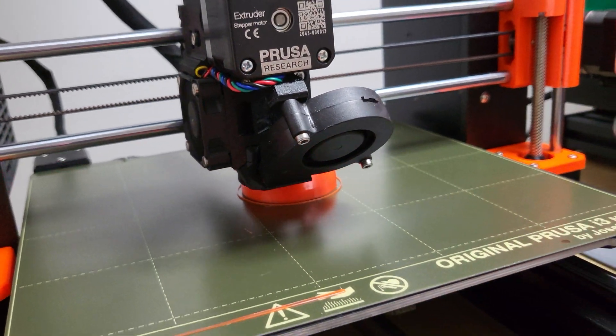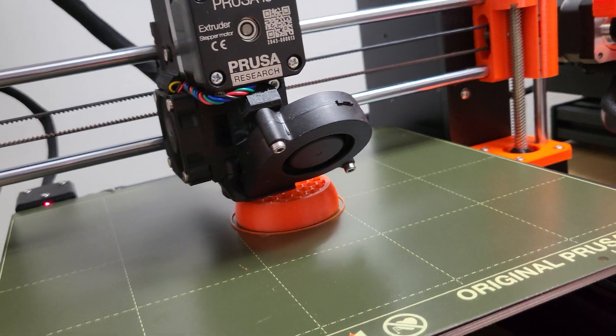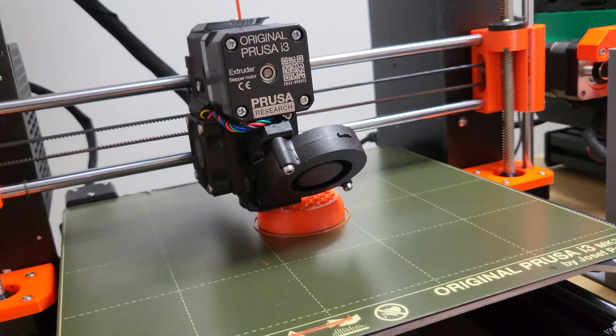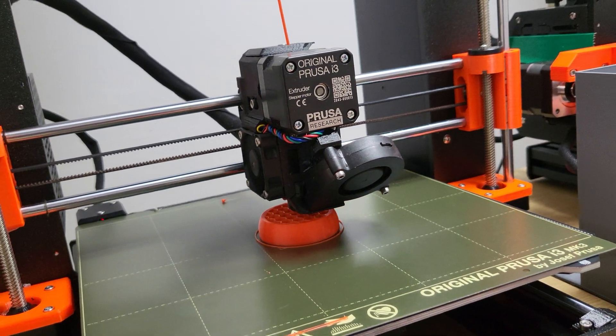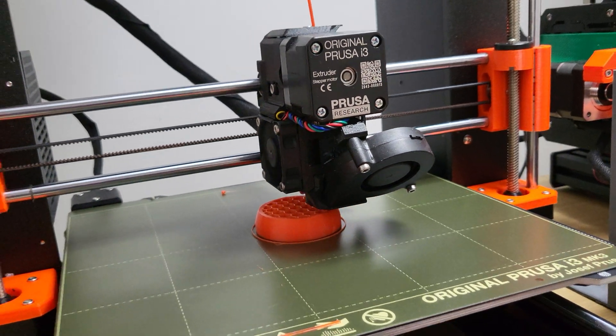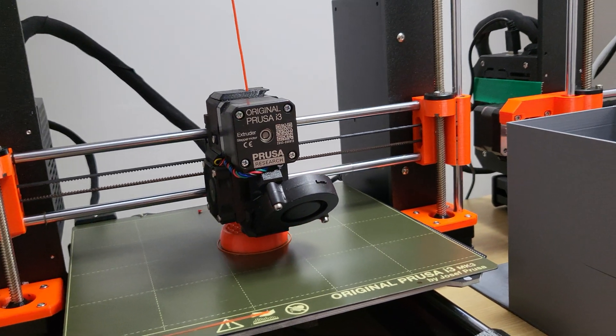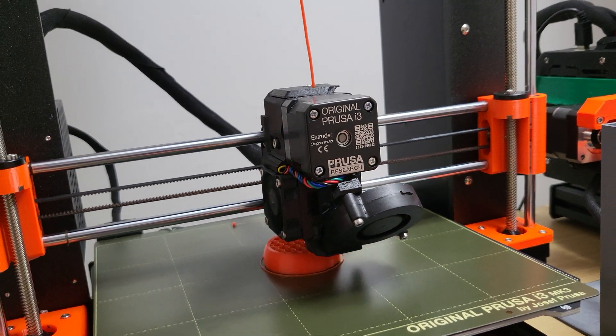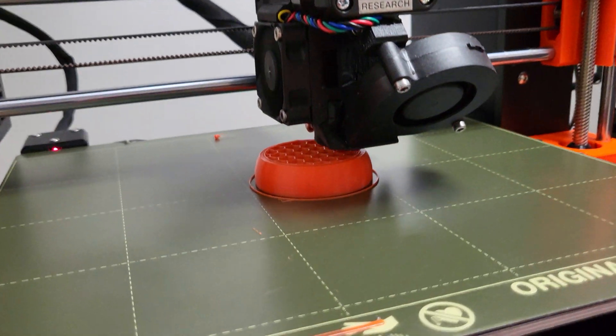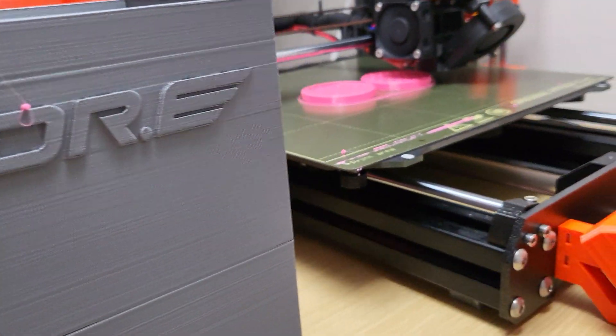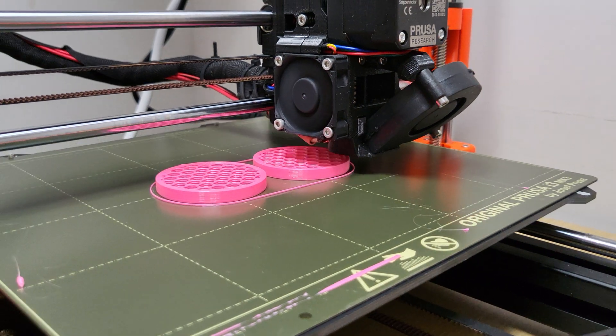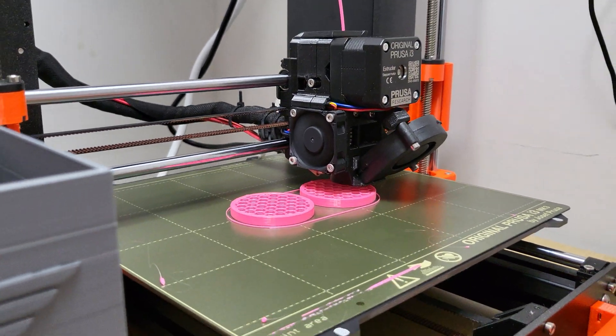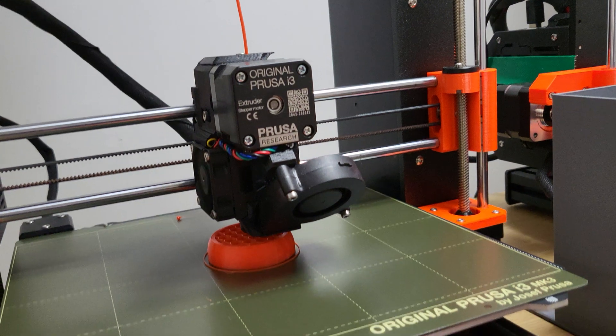200 millimeters per second, exact same speed settings I'm using with my PETG. The only thing I would slow down a little bit is the perimeters I've set around 150, but my infills, which is the most important, is going at 200 with 4K. So of course it might not actually reach those speeds, but this is way faster than any of my other speeds.